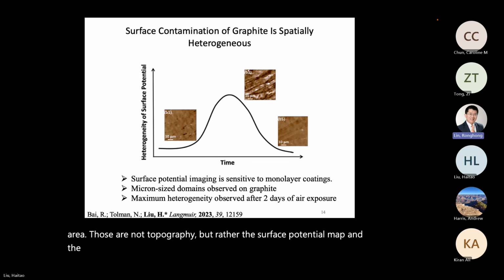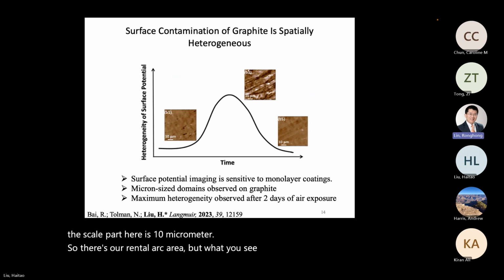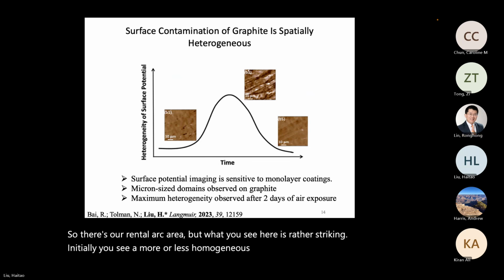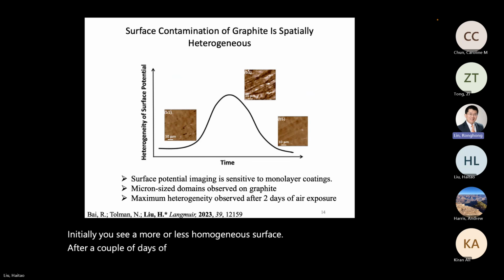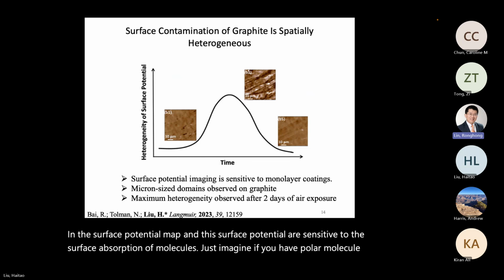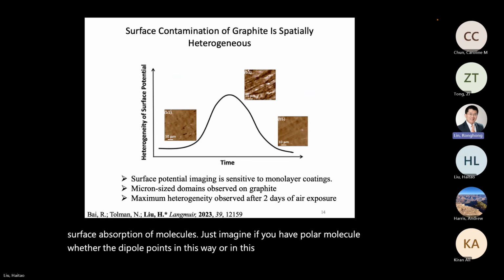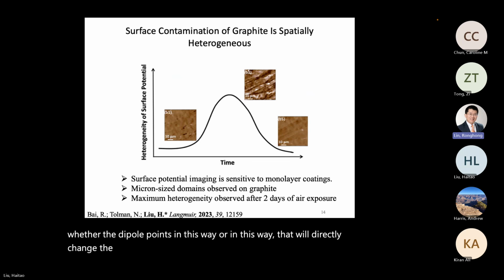And the scale bar here is 10 micrometer. So those are relatively large areas. But what you see here is rather striking. Initially, you see a more or less homogeneous surface. After a couple of days of exposure in air, you start to see this heterogeneous complexity showing up on the surface in the surface potential map. And those surface potentials are sensitive to the surface absorption of molecules. Just imagine you have a polar molecule, whether the dipole points in this way or in this way, that will directly change the surface potential detected by the AFM tip.